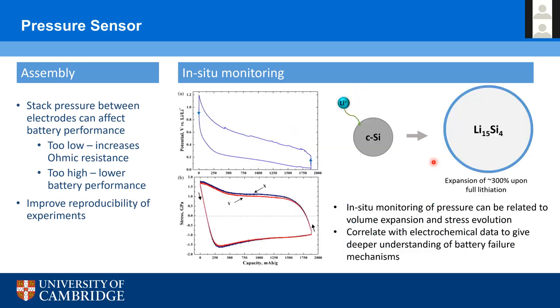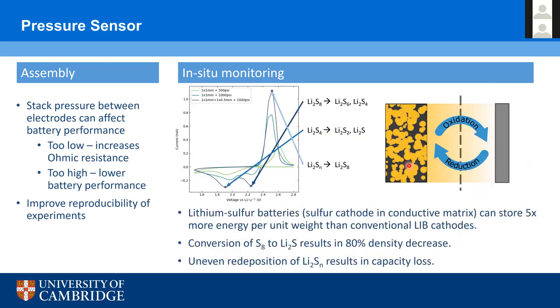And so we have many strategies to try and mitigate this pulverization and improve and extend the cycle life of silicon anodes. But really, we think including a pressure sensor would be really interesting to monitor these changes in pressure, correlate them to the volume expansion, and gain further insight into battery failure mechanisms. I'll hand over to Liam for.